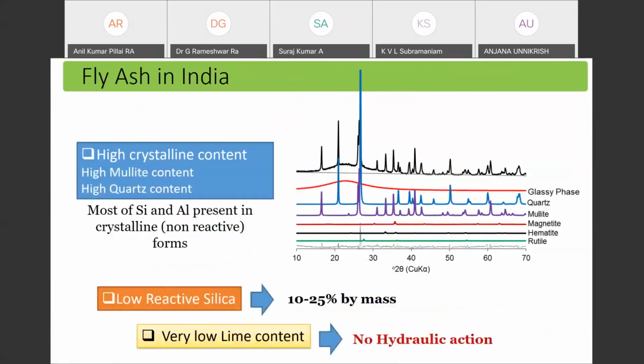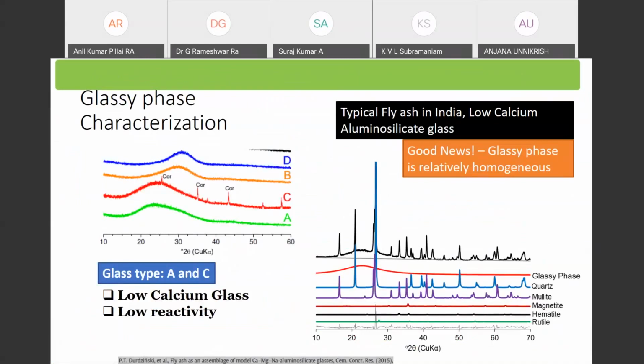So we went further. We started looking at the different glasses that are present that can be formulated. These are the X-ray diffraction signatures of different glasses that we formulated in our lab. These glasses are synthesized. And we found that the low calcium fly ash, which is given by C and A, is the X-ray diffraction signature of the glass that is present in most of the Indian fly ashes. It is a low calcium type glass, the C and the A. And such glasses, as we look at the chemistry, are inherently non-reactive.